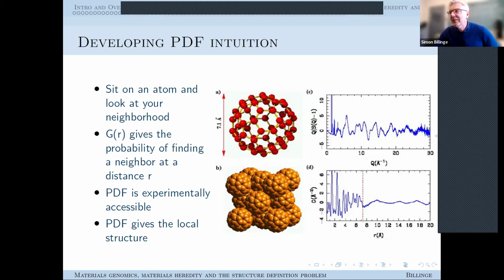And remarkably, this PDF here is a PDF of C60, but it came from this measured data set. So we took actually a powder of C60, we put it into an X-ray beam, we measured the intensity, we Fourier transformed it, and we got this thing, which is exactly the PDF of this C60. So it's kind of a miracle.